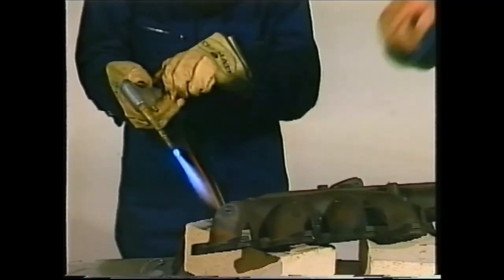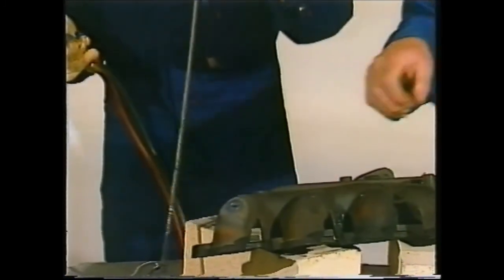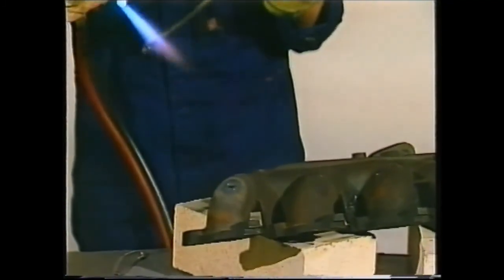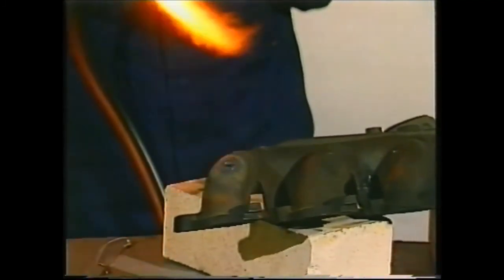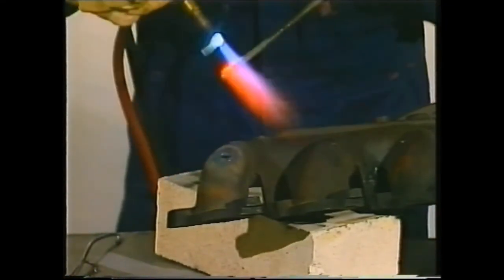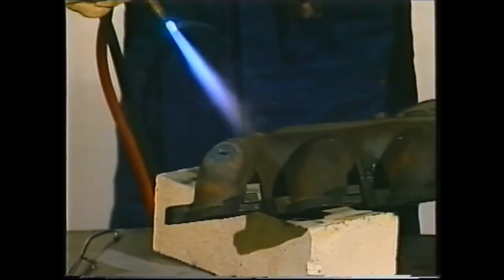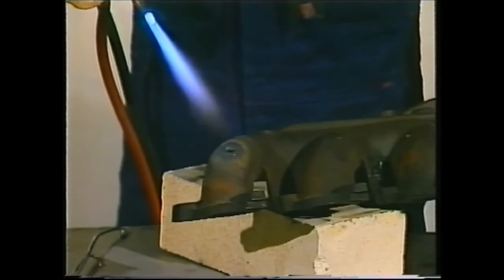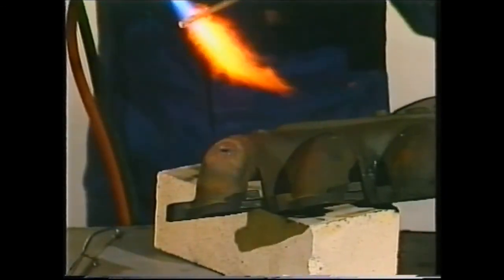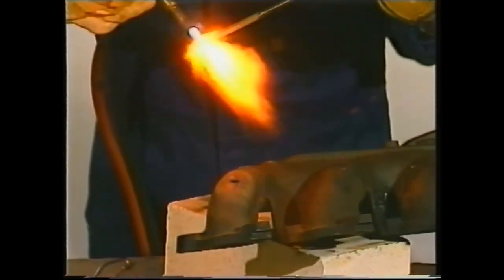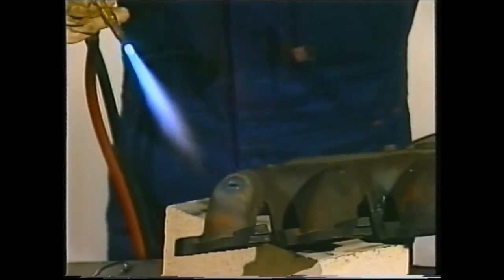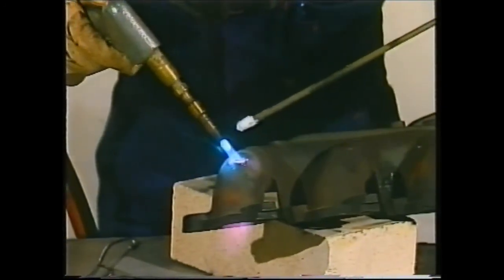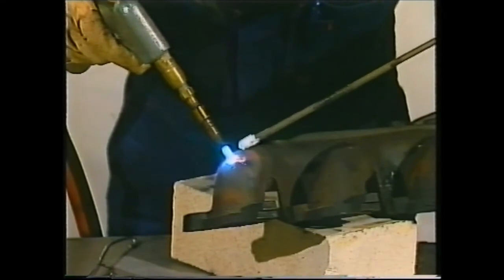And you can see here, again, it clearly shows that narrow, concentrated heat pattern, which is the whole secret of the torch for all of its welding operations. Just using a bit of standard cast iron filler rod and just some standard cast iron flux. You only really require flux with cast iron when it's dirty like this. Clean cast iron wouldn't require flux at all.